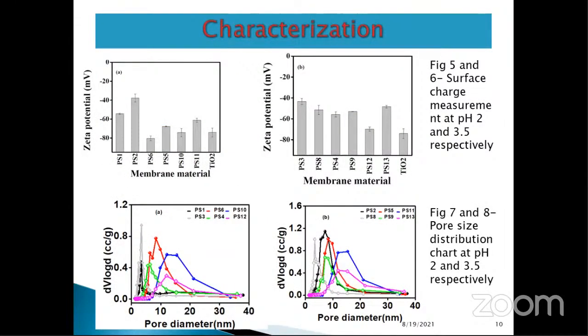Then figures 5 and 6 represent the determination of surface charge by zeta potential measurement. As we can see in figure 6, the zeta potential is less than minus 25 millivolt. So it denotes extreme stability of titania in aqueous solution, and also it suggests that at pH 3.5 the dispersion of titania is stable.